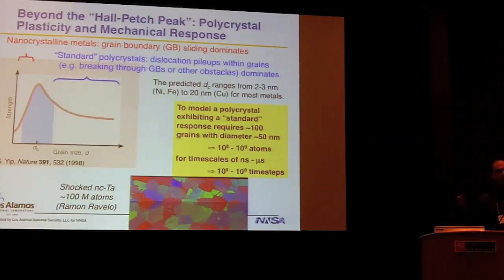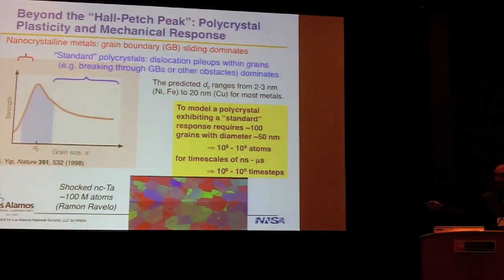But if we want to understand the response of a polycrystal above this nanoscale, if we say we need, say, 100 grains to have a representative microstructure, a grain size well above this turnover of 50 nanometers or so, that puts us in the order of 1 billion atoms. If all we want to do is send a single sound or shock wave through the material, that puts us into timescales of nanoseconds. If we want anything more interesting to happen, we have to follow it for even longer, say microseconds. So we're looking at roughly 1 billion atoms for up to 1 billion time steps.